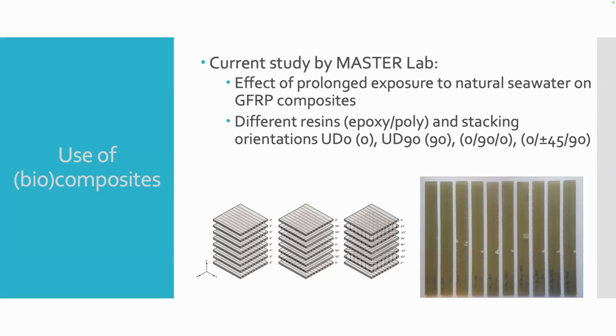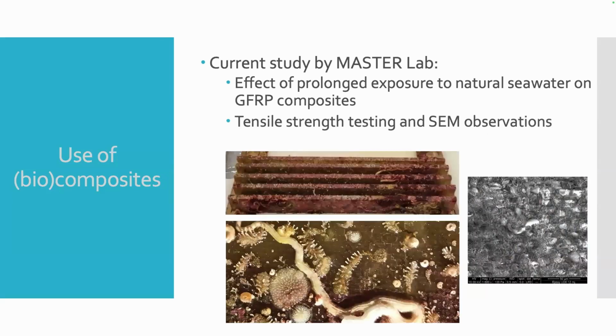This is the study that has been conducted by my PhD student, Goran Vizentin. We made composite coupons of glass fiber composites with 2 types of resins, epoxy and polyester, and different stacking orientations. What you see here are the coupons that were made and exposed to the natural seawater, the natural marine environment, for 3, 6, and 12 months. When we extracted them, that is the first picture up there, we did optical microscopy and scanning electron microscopy on them, and we were surprised to see the number of marine microorganisms that had attached to the surface of this type of composites.